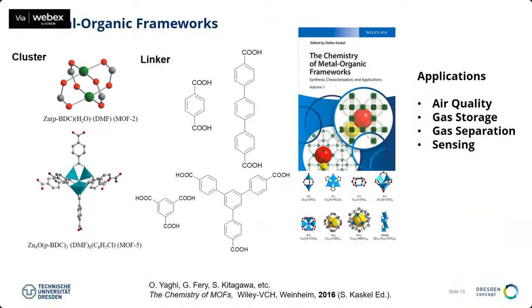And here are some of the pioneers in this field who also contributed to this book: Omar Yaghi, Gérard Férey, Susumu Kitagawa, but there are many more pioneers who pioneered the field of metal organic frameworks. Omar Yaghi with MOF-5 was the first structure, of course, which produced a material with very high specific surface area, 3,000 square meters per gram. I mean, if you buy or rent an apartment in Milano, then 3,000 square meters would be really something very, very expensive. But we can make this in 1 gram of material. And maybe it's difficult to live in a MOF, but at least we have a very high specific surface area.